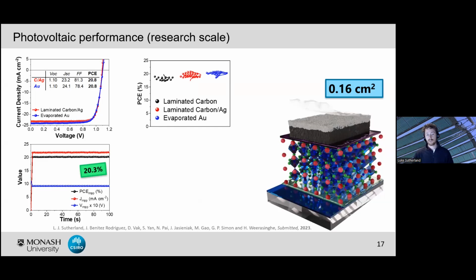And again, if we look at the devices in the batch, we can see, again, a great comparison between our laminated electrodes and our evaporated gold. We see that the major difference is due to a drop in the JSC, which we attribute to a lack of back reflection from our carbon electrode in comparison to the highly reflective gold electrode, which allows for that secondary light absorption.